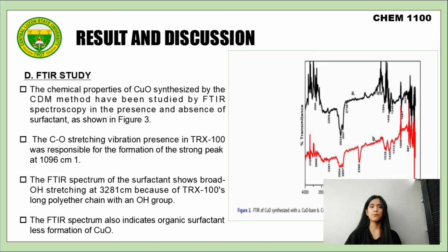The FTIR spectrum of the surfactant sample shows broad OH stretching at 3281 cm⁻¹ because of Triton X-100's polyether chain with an OH group. The FTIR spectrum also indicates organic surfactant-less formation of copper oxide. The next slide will be discussed by Ate Rani Lingjoy.